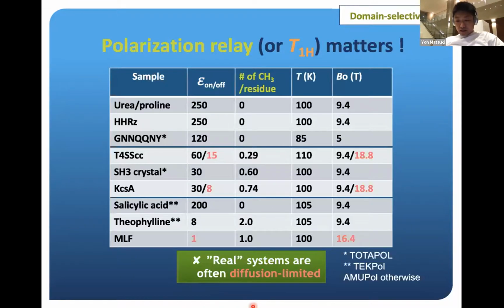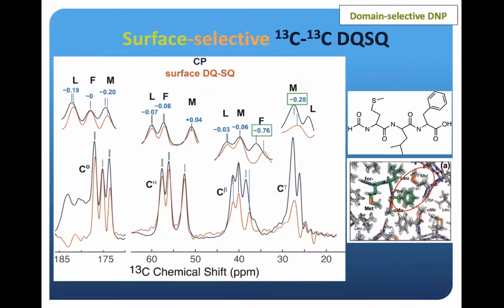Basically the glycerol signal was too small, because we wetted the crystalline MLF and thoroughly drained the glycerol matrix, so as not to disturb the further analysis. So it's kind of difficult to see it. But in principle, it's possible to do. Yeah, it might be interesting to do an experiment with labeled glycerol where you measure that. Yeah, that's a good point. Take a look at this. You see these slides, right? This is MLF. We're almost not seeing any glycerol peaks here at 60, 65. So yeah, let's think about it.